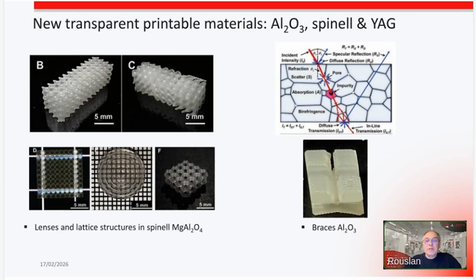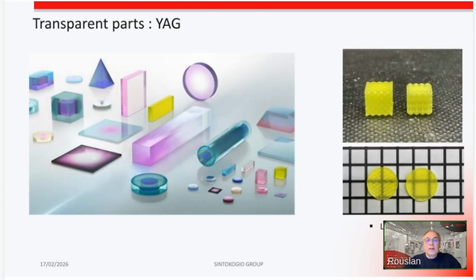So here are examples of alumina, which is translucent or transparent alumina. It's not really standard alumina, it's a little bit different powder, but with some post-process like HIP, we can get translucent or transparent parts. YAG is another example of transparent ceramic parts. These materials are not available as a standard, but they can be supplied on request or co-developed with the customers based on proprietary or even commercial powders.